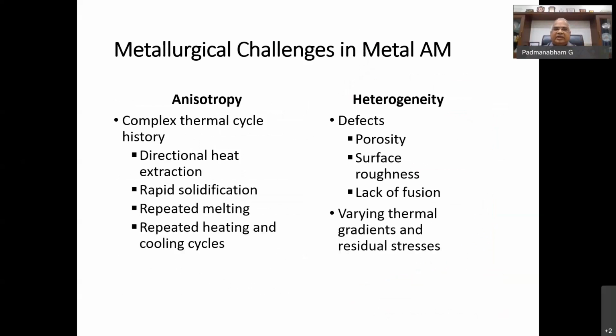Now we talked about the technology, the process challenges, and the economic challenges. Now let us look at a more in-depth analysis of the metallurgical challenges involved in metal additive manufacturing. I talked about the anisotropy, that is the behavior in the XY plane and in the Z direction. Why does this happen? As the heat dissipation while melting and solidification happens through the build direction, it is higher compared to the other direction. So solidification in that direction results in anisotropy in grain morphology and consequently in mechanical properties.